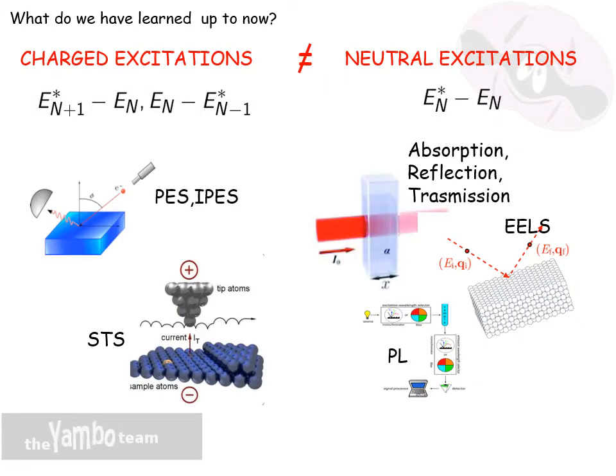The first point that we have learned is that charged excitations, probed by experiments like photoemission, inverse photoemission, or scanning tunneling spectroscopy, are formally different from neutral excitations, probed instead by experiments like absorption, reflectance, transmission, or energy loss spectroscopies, where the electrons are excited to unoccupied states but do not leave the system. So keep in mind that in principle the electronic and optical gap of a material can be quite different, and we will see when and why this happens.